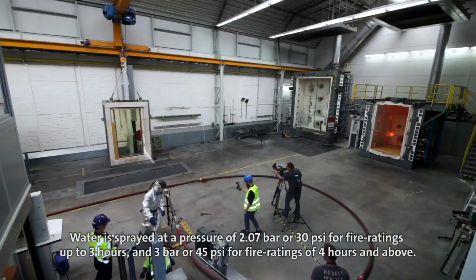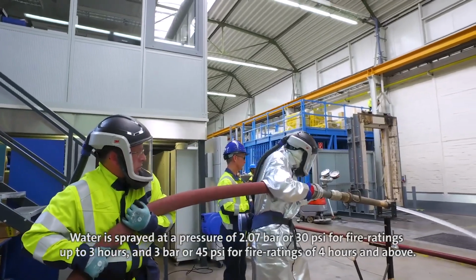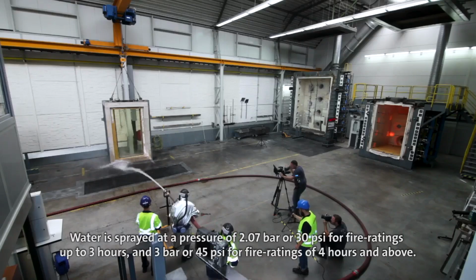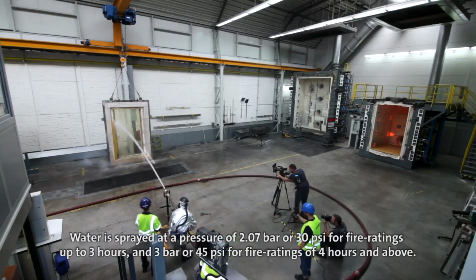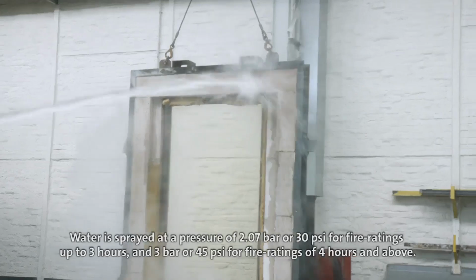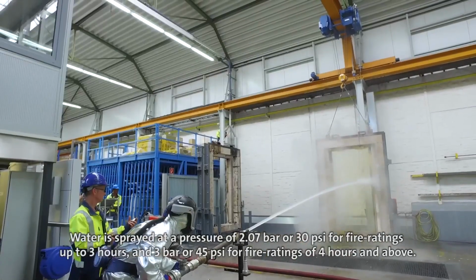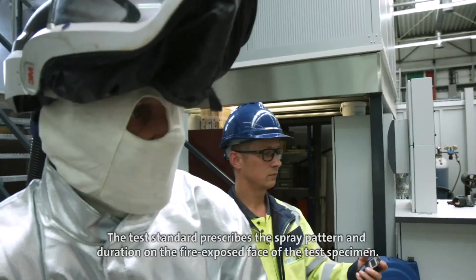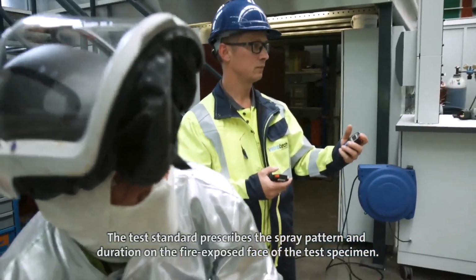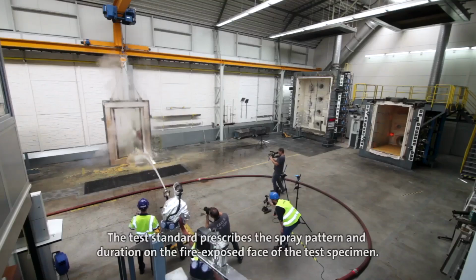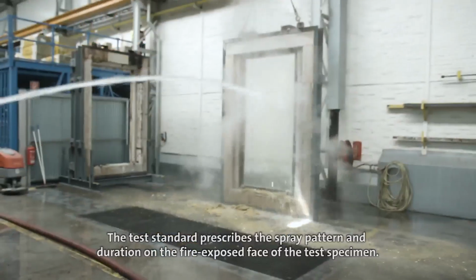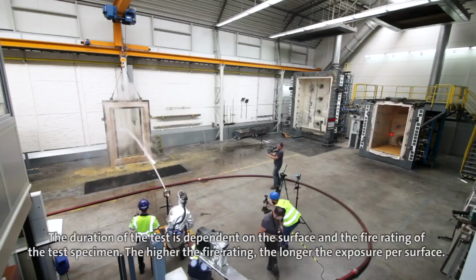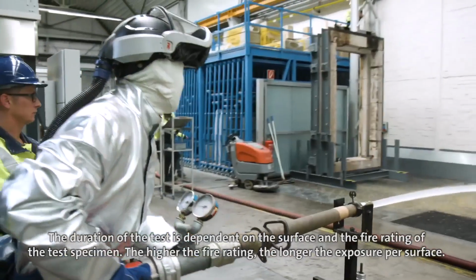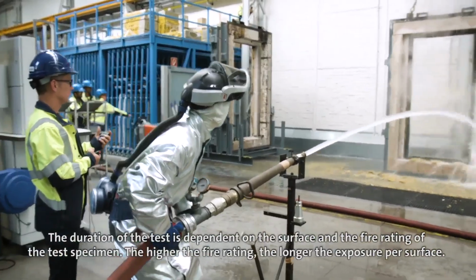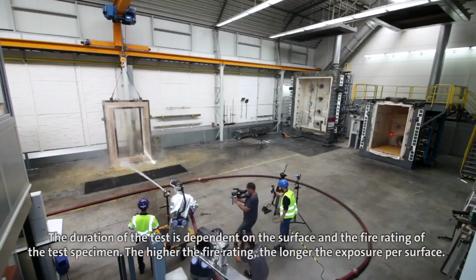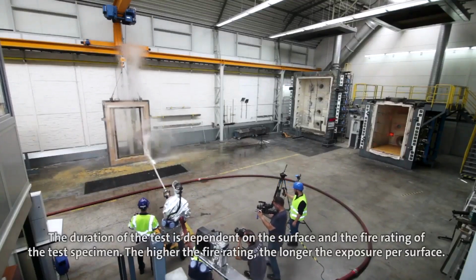Water is sprayed at a pressure of 2.07 bar or 30 psi for fire ratings up to 3 hours and 3 bar or 45 psi for fire ratings of 4 hours and above. The test standard prescribes the spray pattern and duration on the fire-exposed face of the test specimen. The duration of the test is dependent on the surface and the fire rating of the test specimen. The higher the fire rating, the longer the exposure per surface.